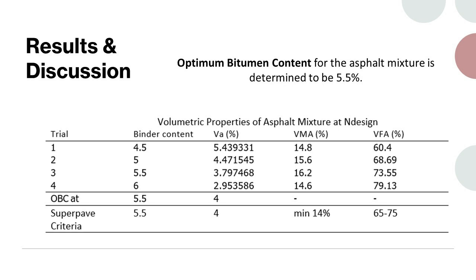Based on the obtained air void content and other considerations within the Superpave mix design methodology, the optimum bitumen content for the asphalt mixture is determined to be 5.5%. The selection of this specific bitumen content is aimed at achieving the desired balance of performance characteristics such as durability, stability, and resistance to moisture damage.